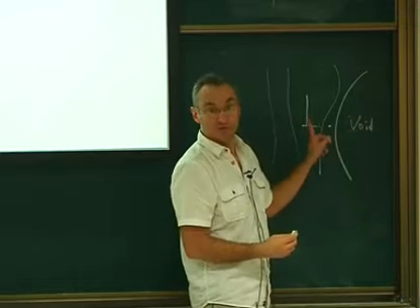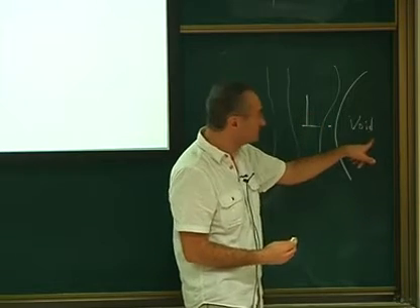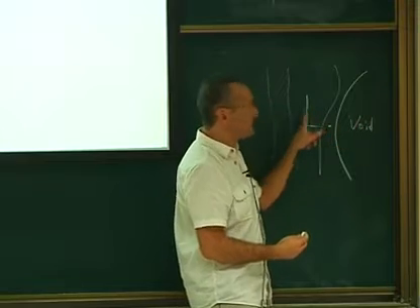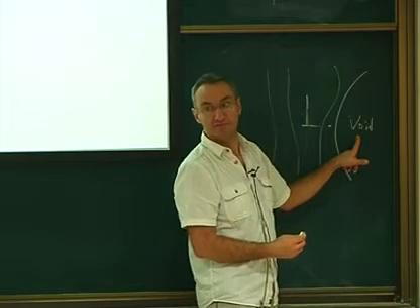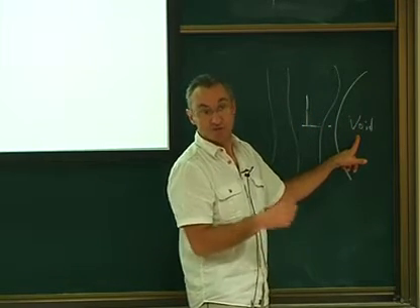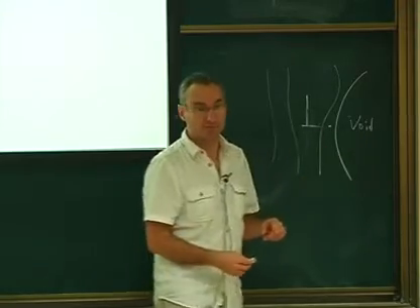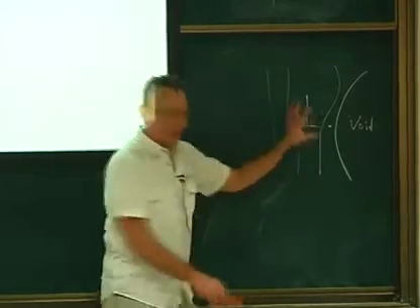And this is exactly a change of elastic moduli. This is a zero modulus compared to a bulk modulus. So you see that the change of elastic moduli also plays a role when you have obstacles. And this is something that we need to implement in DD if we want to take into account this effect. Okay? So I think that was important to stop here, and I will show you how we do that.